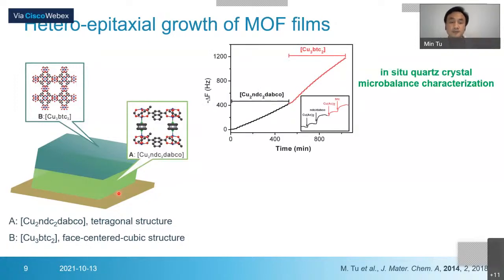So by using the layer-by-layer method, we can first have MOF A at the bottom, and we can continue the growth of MOF B, copper BTC, and have both layers on the surface. Here we can see this by in situ quartz crystal microbalance characterization. The black one is the first layer deposition, and we can see the layer-by-layer growth. It is a gravimetric measurement, so we can measure the mass change on the surface. We can see the layer-by-layer feature of the first layer and of the second layer. At the interface, in the last cycle of copper NDC DABCO, we have copper acetate, then NDC and DABCO. Then we deposit copper acetate, and we have the BTC linker.